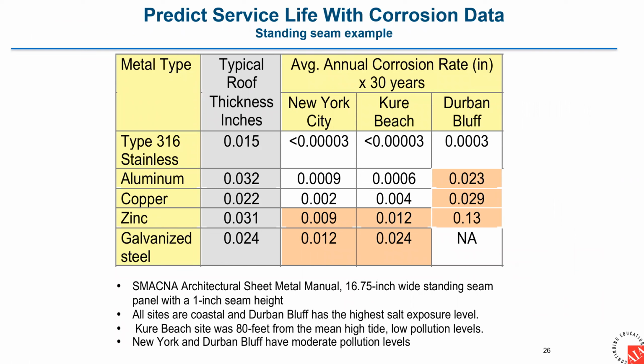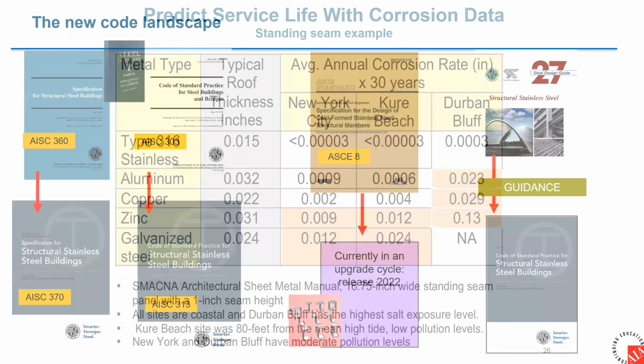I've used the SMACNA Architectural Sheet Metal Manual, and I've shown the typical roof thickness. I multiplied the average annual corrosion rate for New York City, Kure Beach on the Carolina coast, and Durban Bluff in South Africa, and in any location where at 30 years we've lost at least a third of the thickness, we have to assume that we have perforation. And that will also, of course, affect the overall performance in a structural application as well.